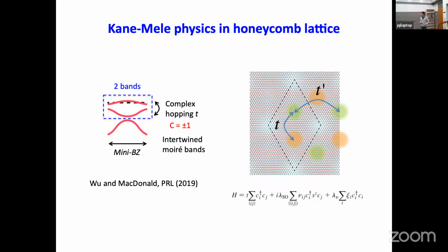In fact, the low energy physics of the two-band model can be mapped to a model on a honeycomb lattice instead of the triangular lattice, known as the Kane-Mele model, that describes the nearest neighbor hopping t and the next nearest neighbor hopping t prime, which is like an effective spin-orbit interaction. And then you can also put an energy difference between the A and the B sublattice sites on the honeycomb lattice. That would be the on-site potential difference, which is tunable by an electric field. So the Hamiltonian in this kind of two-band system can be continuously tuned by simply applying an electric field, and that would change the potential difference between the A and the B sublattice sites.